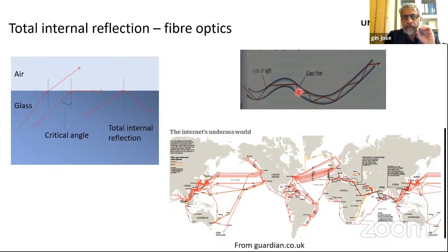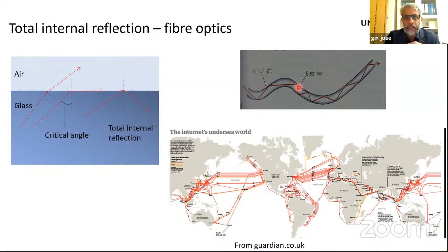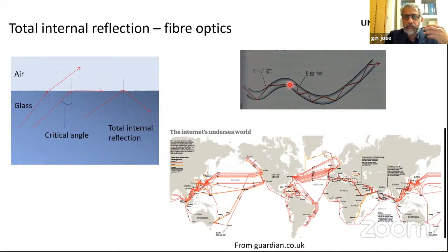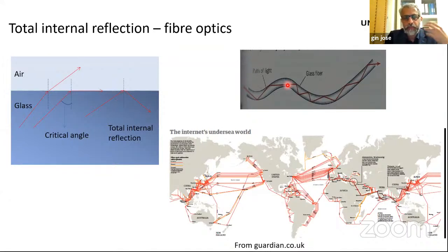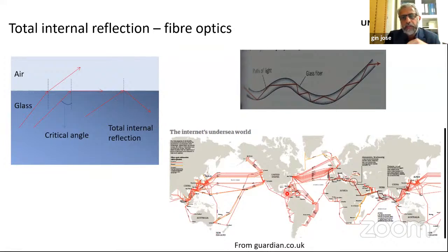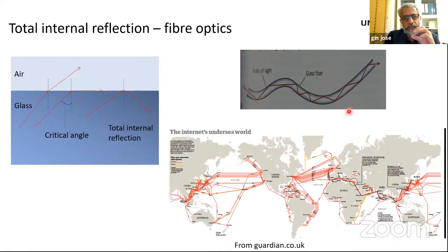The most suitable wavelength for transmission in silica glass is around 1550 nanometers. Glass is mostly transparent and transmits light, but it is most transparent around 1550 nanometers — where attenuation is lowest. That's why this particular wavelength range is used for optical fiber communication connecting different continents.